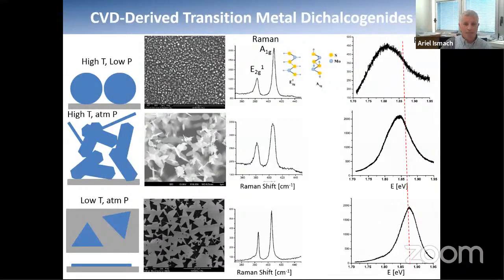So when we talk about the one layer, especially in this family of 2D materials, the transition metal dichalcogenides, which is basically an array of transition metals sandwiched between two chalcogens, the importance of having this as a single layer you can see from this first paper in 2010, where they proved that these materials, as we knew for tens of years, are what is called an indirect band gap semiconductor, which means that in order to have a transition from the excited state to the valence band, you need a momentum change and also an energy change. So the probability of photoluminescence is very low, as you can see here in green. This is the photoluminescence measurement in a two-layer MoS2 in this case.